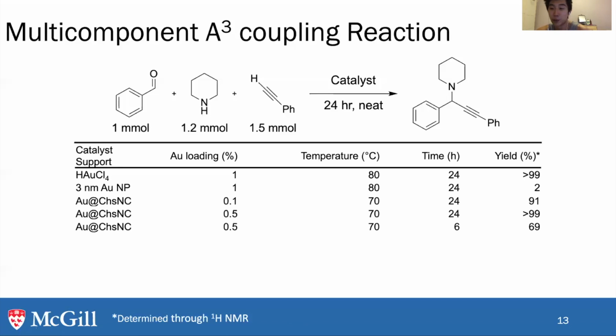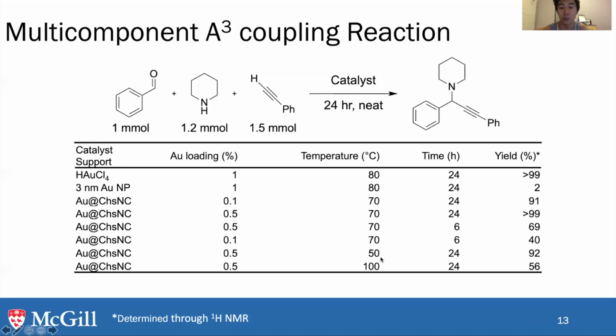Now, if we decrease the time, it still provides a relatively high yield. And if we decrease the loading, of course, the yield decreases. However, if we go to relatively benign conditions of only 50 degrees Celsius as opposed to 70, you can see that we're still getting higher than 90% yield. And one interesting thing is that if we're using 100 degrees Celsius instead of 70, we actually see a decrease in yield. This may be due to the fact that we're decomposing the intermediates at such a high temperature.